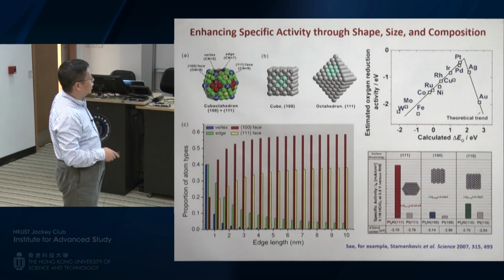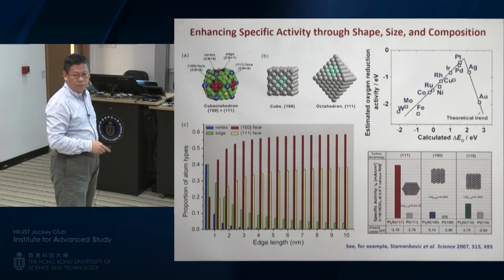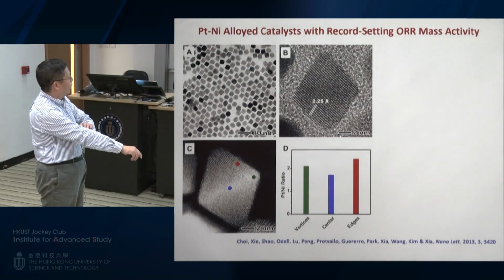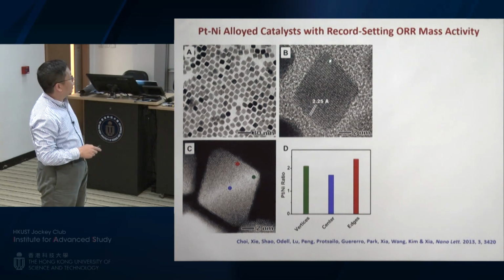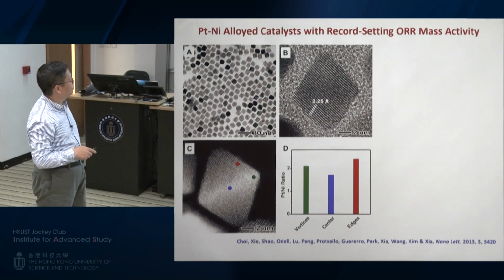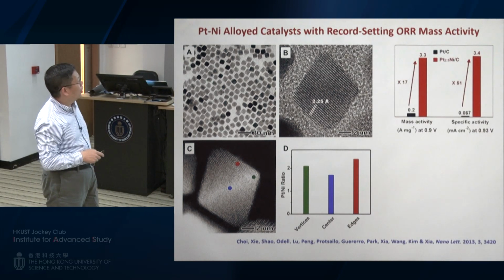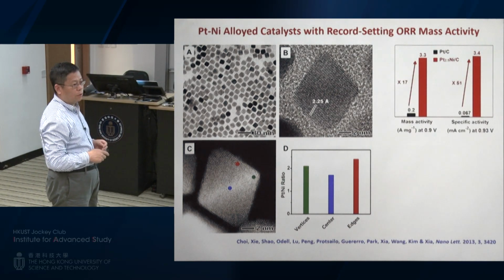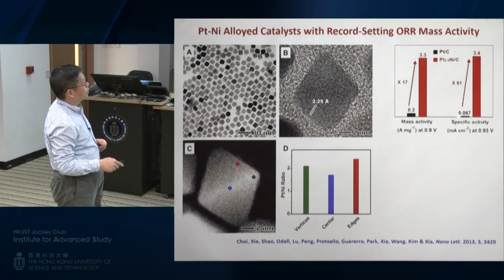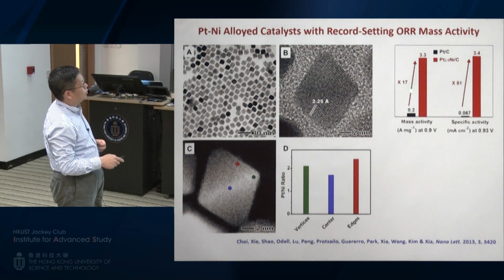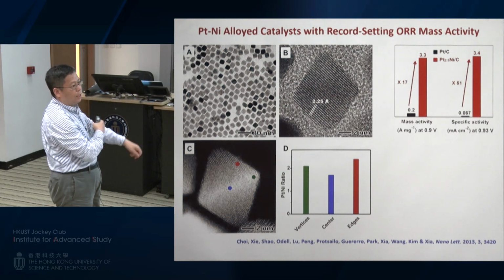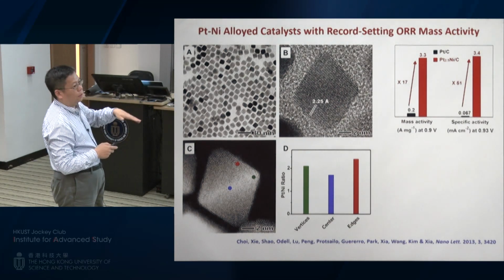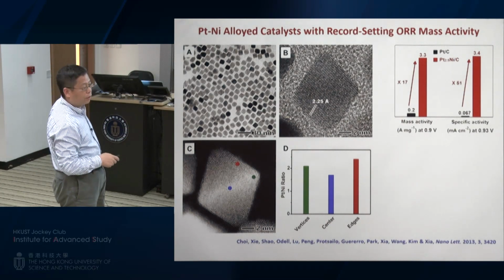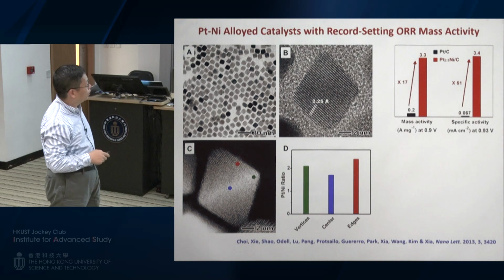So when we worked with Minghua 6 or 7 years ago, we managed to make some Pt nickel alloyed octahedra, and Minghua did some tests. This kind of catalyst turned out to be quite remarkable, as we would expect. If you look at their specific activity compared to the Pt/C, it's increased by almost 50 times. And the mass activity could be increased by 17 times. So that means if you use this catalyst, the platinum loading could be reduced by 17 times. That's basically the simple mass calculation.